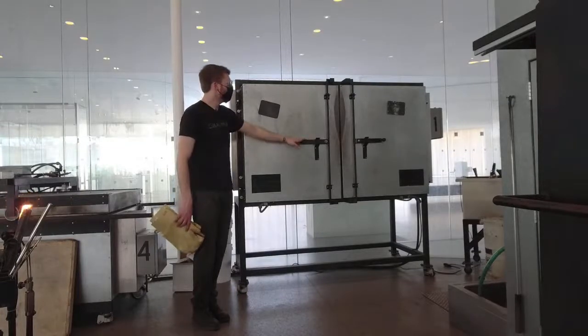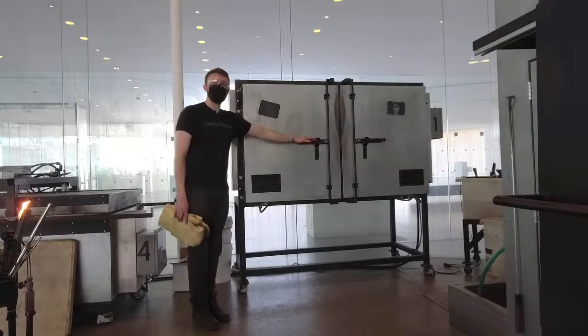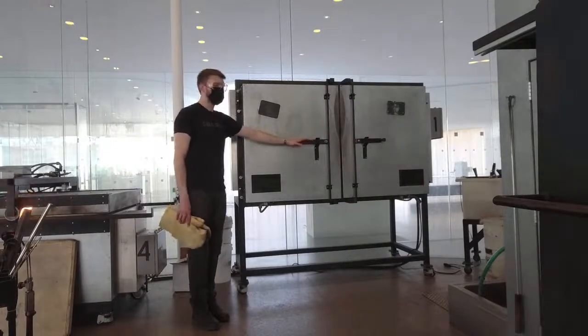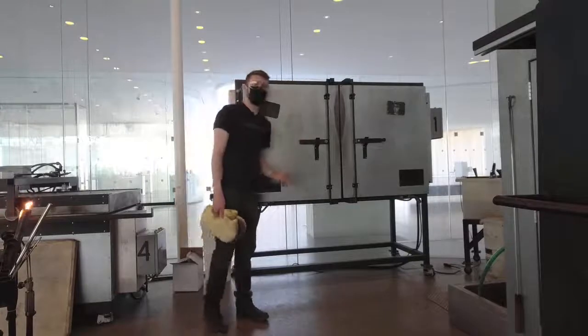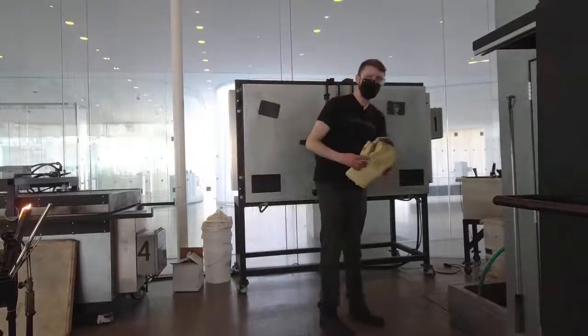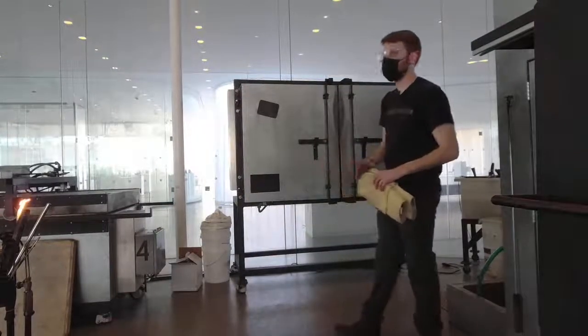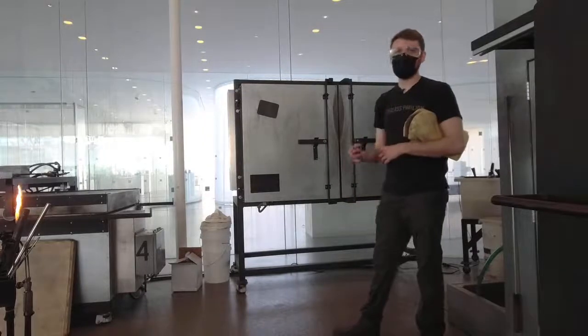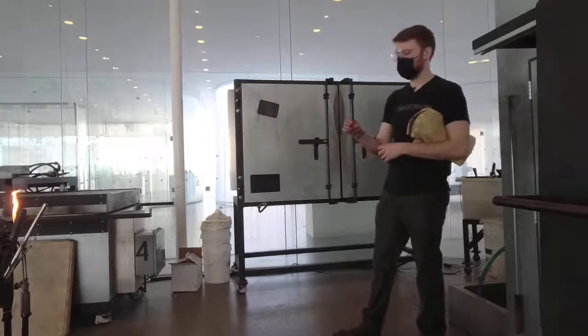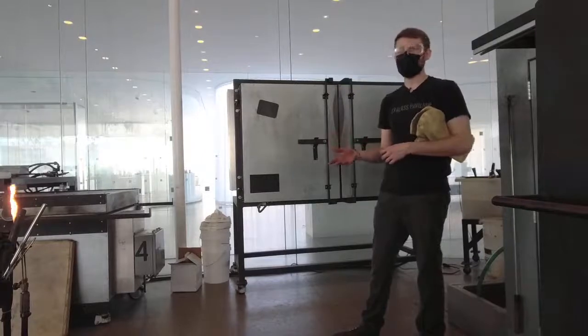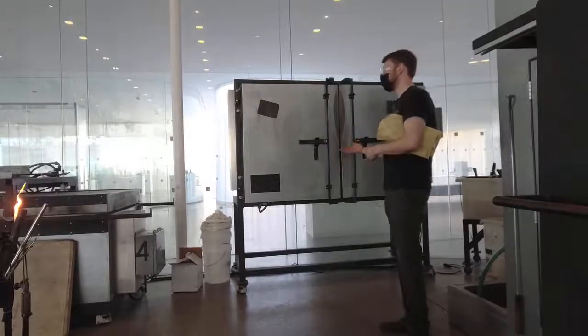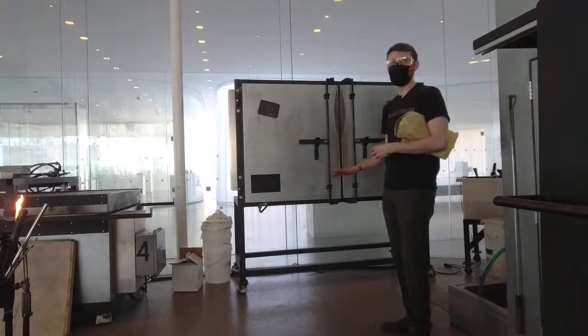So at the end of the night, we're going to send this down on a cycle, and our cycle here is maybe about 16 to 18 hours. And that's just also dependent on the thickness of the glass. So Colin's form to get that nice handkerchief shape was very, very thin. It was only a couple millimeters thin. The thickest portion was the foot at maybe about an inch thick. And that's plenty of time to anneal the glass and alleviate the stress in that 16 to 18 hour time frame.